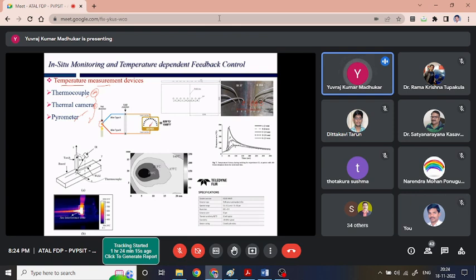Yes, of course, in case of a WAM application in which we have to deposit a number of layers, using the thermocouple is probably not going to give us a good result, because in this case, at most we can place our thermocouple at the bottom. After that we cannot do it. Otherwise, after every layer we have to drill and place the thermocouple. So for a laboratory experiment or trial experiment, it may be okay. However, when we talk about a ready-to-use component that can be used on an industrial platform, it is probably not going to give us a good solution. So a thermocouple may be used at the laboratory level. However, when we talk about actual part building, the thermocouple is possibly not a good choice. So the other option we are left with is the thermal camera.